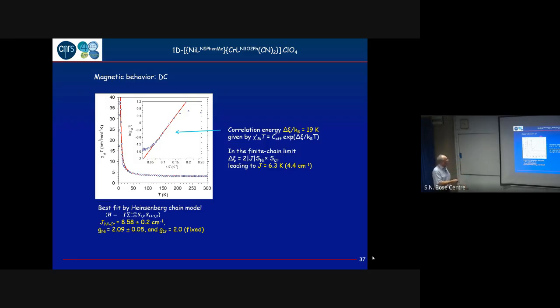So this was just to show that from such data we can also extract what I introduced before, that is a correlation energy, because when the exchange interaction comes into play, you have an exponential growth of the magnetization of your system. And so this is the log of χT versus inverse T, and this is the linear part. And if you analyze that, you get the stabilization energy coming from the exchange.